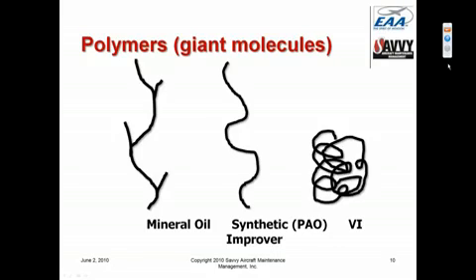They pulled their AV1 full synthetic oil off the market back sometime in the 90s, and we don't have full synthetic oil anymore. We do have some semi-synthetic oils like Aeroshell 15W50 and Exxon Elite that have some polyalphaolefin in them. It's about 50-50 for Aeroshell 15W50. It's about 25% synthetic for Exxon Elite. But these oils all have generous amounts of mineral oil in them in order to keep the engines clean. This is not a problem that we have with automotive engines, and fully synthetic oils work really well in automotive engines other than diesels, which are pretty filthy, just like our aircraft engines are.